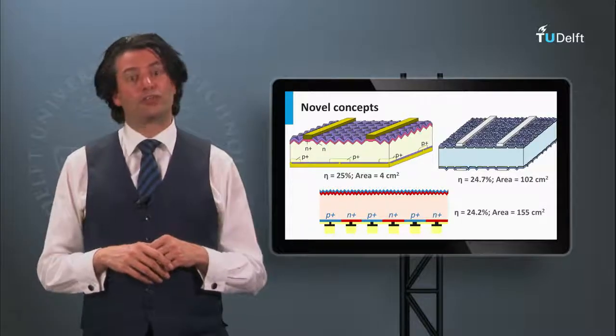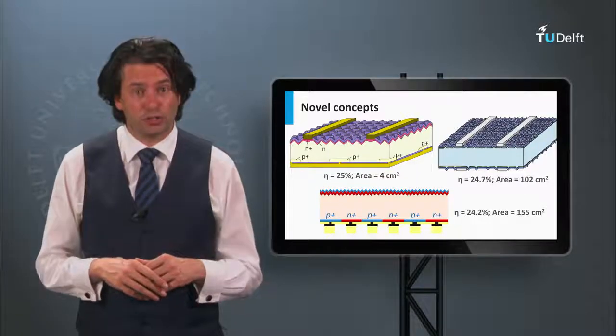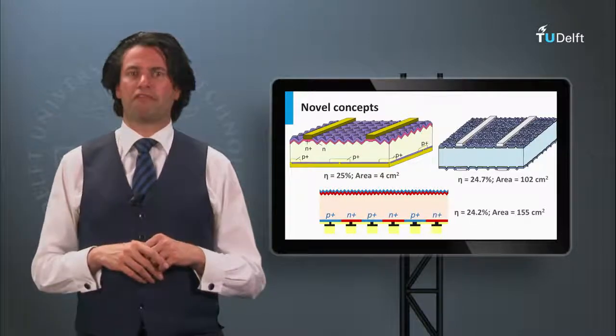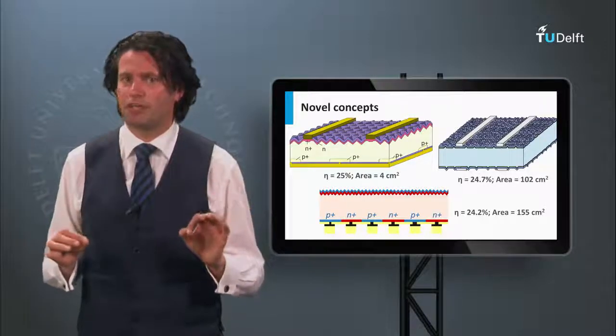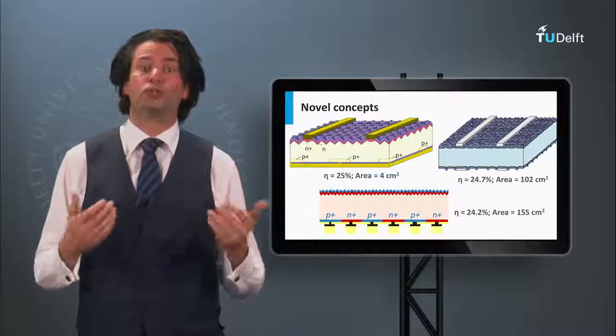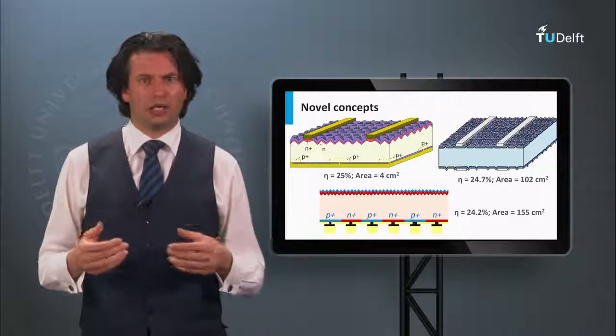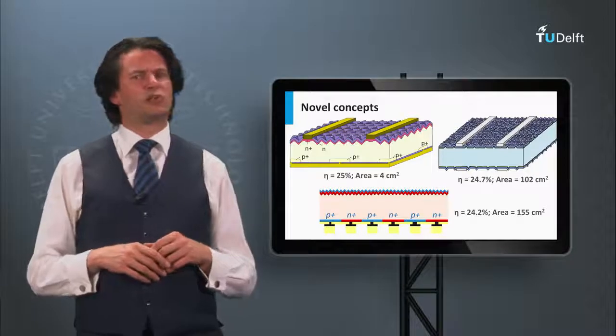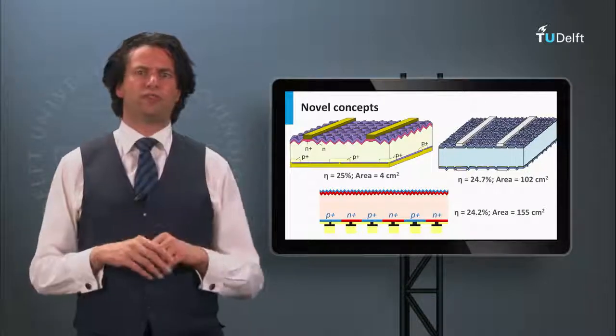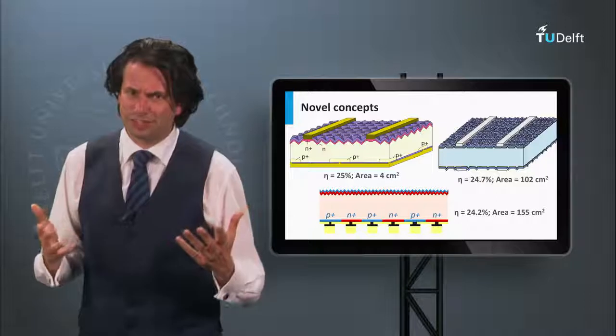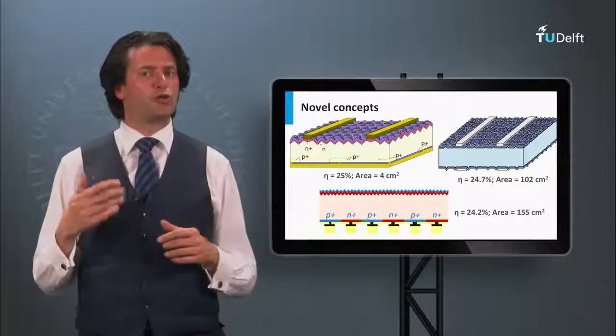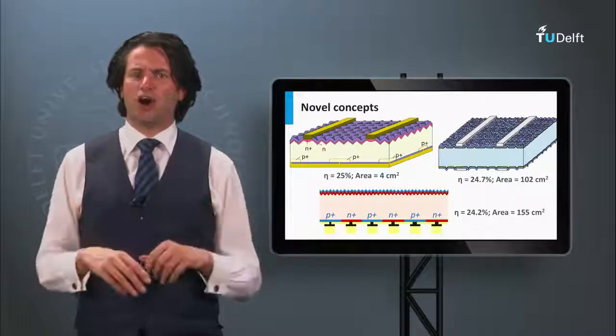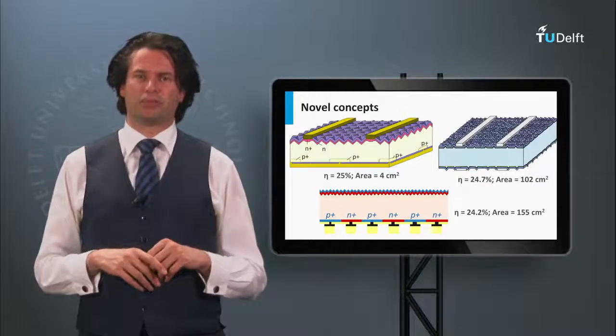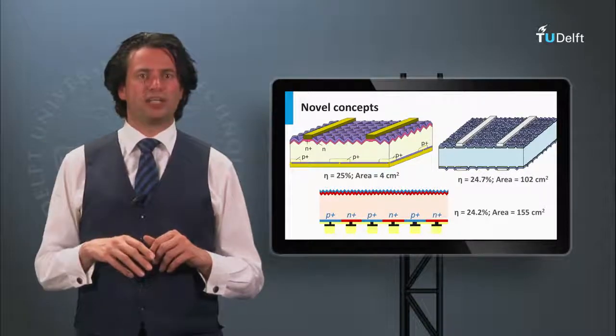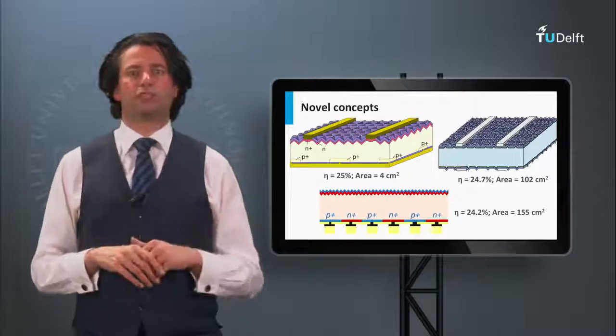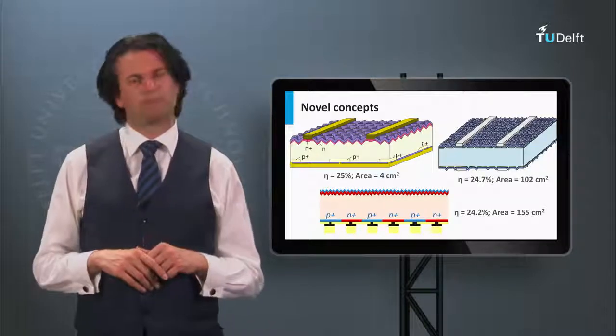Finally, for the crystalline silicon-based heterojunction solar cell, Panasonic achieved an efficiency of 24.7% on a wafer size of 102 square centimeters. The efficiencies for multicrystalline silicon solar cells are lower as the wafer quality is lower. The best efficiency achieved is 19.5% by Q cells on a wafer with a size of 243 square centimeters. This is around 5% absolute below the record efficiencies based on monocrystalline silicon wafers.